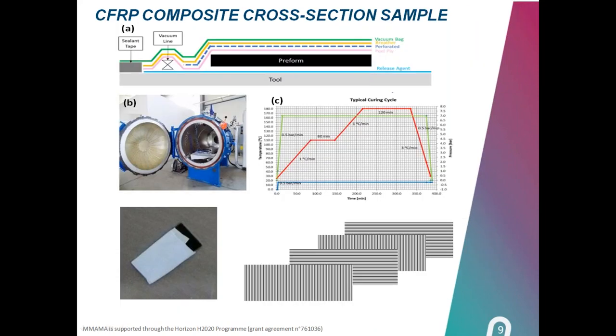Using this prepreg that we produce, we can go and manufacture some composite parts. Usually prepreg is a single layer. We use multiple layers of this material in different orientations, as you can see at the bottom right. We use a typical vacuum bagging sequence, and in order to consolidate the material, to compact it and to cure it so that the polymerization proceeds, we use an autoclave, which is aerospace rated, and then you can see a typical curing cycle here. We have temperatures up to 180 degrees, pressures up to 7 bars, and usually vacuum goes from -1 to 0.